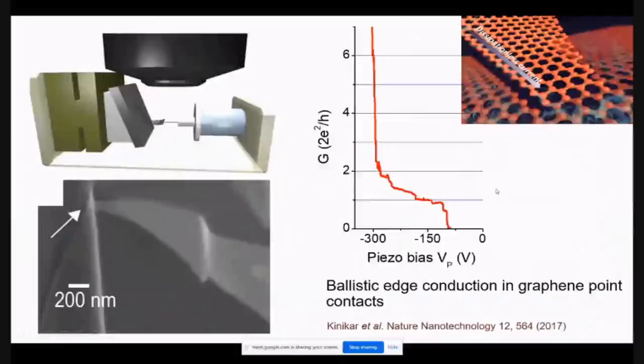Now, we were one of the first set of people to actually show that zero energy states could host dissipationless current even at very high temperatures, at room temperature. So you can see the conductance of these zero energy states can actually be e squared by h, which essentially is the quantum of conductance, like a one-dimensional conductance state, and this quantization was observed at room temperature. So this is where you can use graphene edges for making circuits.